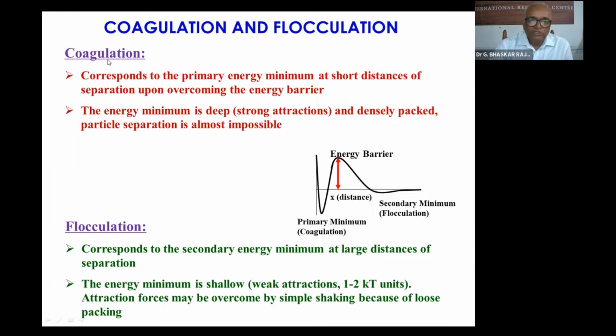Coagulation is usually achieved by putting in inorganic salts, for example alum, or iron salts like ferric hydroxide. All these are useful for coagulation. So when you use alum or ferric alum, these coagulations can be achieved. And then the forces between the particles are very strong, the energy barrier is very high. That is why they get compressed.